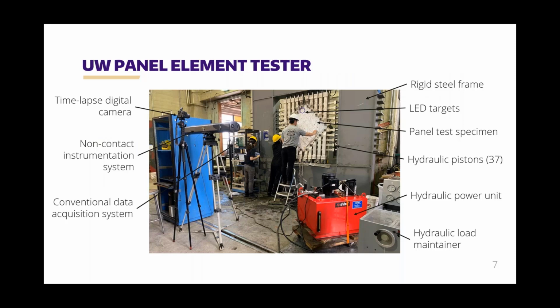We have this panel element tester. And so this is what that looks like here. So you can see we have a number of both conventional data acquisition and non-contact instrumentation. But we will start here with the frame. You can see a big rigid steel frame here in gray. Then you can see the panel there in the middle, and attached to that panel are a bunch of pistons, 37 pistons in all. Those are attached to actuators, which are able to control the in-plane stresses that are imposed onto that panel. And so in this series of tests, we're looking at subjecting them to shear. You can see that we have our LED targets there, and you can see that, of course, we have some hydraulic systems there that are controlling this all precisely.